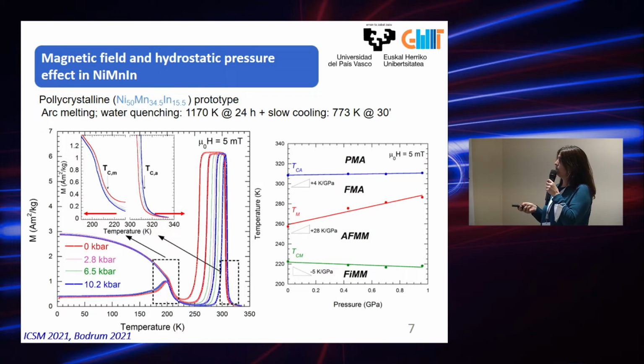We can see that in the case of the Curie temperature of the austenitic phase, the pressure increases this temperature, but in the case of the martensitic phase, this temperature is decreasing. We can see here how we have different phases in this phase diagram, going from a low temperature ferromagnetic martensitic phase to an antiferromagnetic one, and then to the ferromagnetic austenitic phase and then to the paramagnetic one. And we see how, in the case of the pressure, the structural transition goes to high temperatures, and also the magnetic transition of the austenitic phase, but in the case of the martensitic one, it goes down.